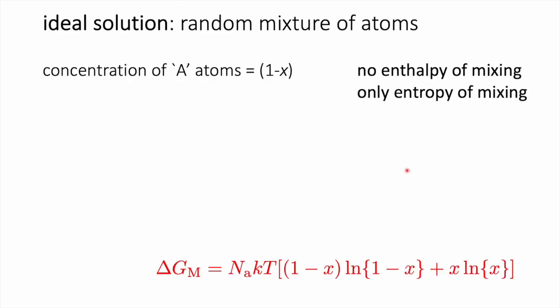Now, I've previously mentioned the concept of an ideal solution, where A and B atoms mix at random. Basically, there is no enthalpy of mixing. We only consider the entropy of mixing. So the free energy of mixing is simply given by Na, which is Avogadro's number, the Boltzmann constant, and temperature times this term which we derived from the configurational entropy. So there's no enthalpy of mixing and only an entropy of mixing.